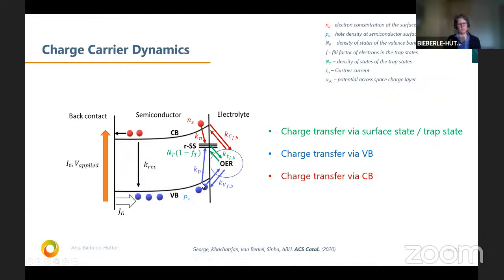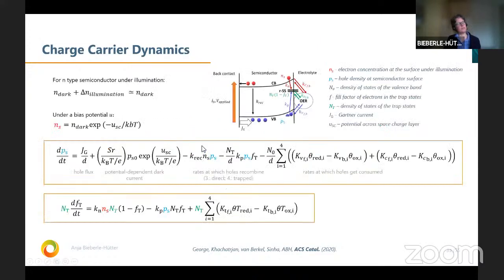We have a conduction band and valence band, and we have surface states here. And when we include this charge carrier dynamics, we include the charge transfer via valence band, via conduction band, and via surface states. And why this is such a big step is what you see here. In the first paper, we assumed that the hole density is a fixed value. And here you see the hole density is a function of the hole flux, of the potential dependent dark current, of the rates at which the hole recombines, the rates at which the holes get consumed. And you see that, for example, the hole density comes in here at several parts. And similar when we calculate the density of states of these trap states, for example.